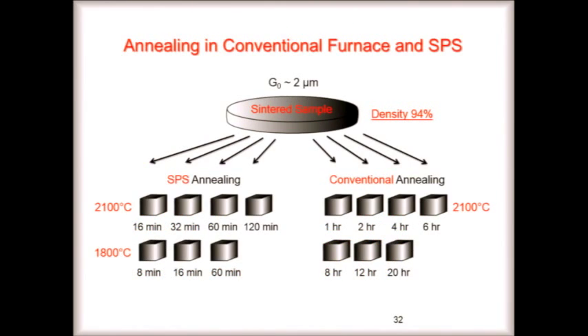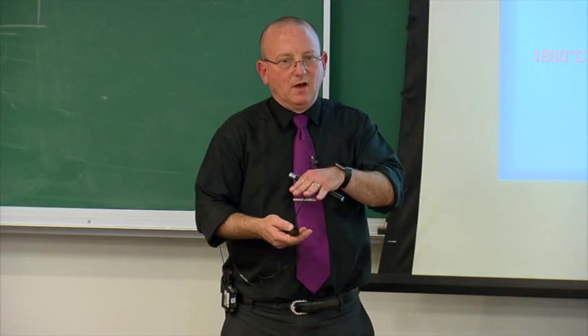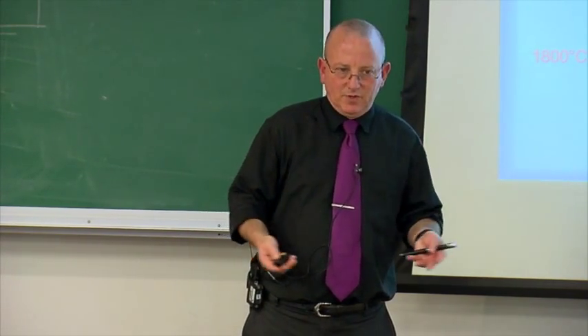We took these samples and sectioned them, and then we did conventional annealing experiments, and then we did annealing with SPS. I didn't have a flash setup, and some friends in the south of Israel had an SPS and were willing to run these annealing experiments. We didn't apply pressure. The rams were brought down to make contact, but the pressure was the minimal that we could do.